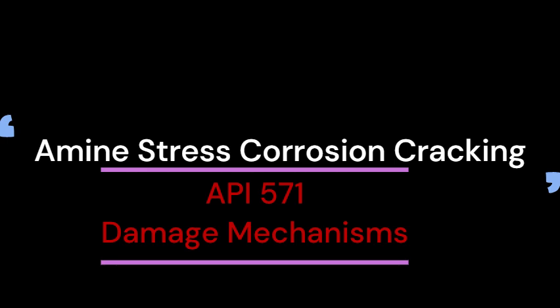Right. And the third factor, temperature. Usually hotter means faster corrosion, right? Generally, yes. Increasing the temperature definitely makes amine SCC more likely and more severe. But here's the kicker, the really crucial part. Uh-oh. There's no real safe low temperature? Cracking has actually been reported all the way down to ambient temperatures, especially with MEA. Wow, okay, so you can't just assume because it's running cool, you're safe from this specific mechanism. Not at all. And that fact really drives the prevention strategies we have to use, regardless of the normal operating temp.